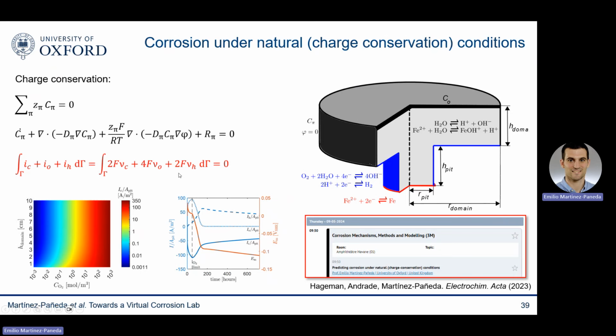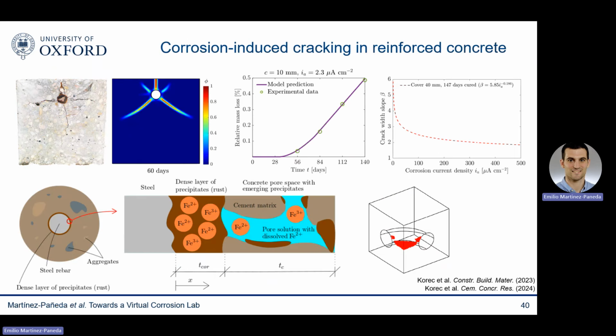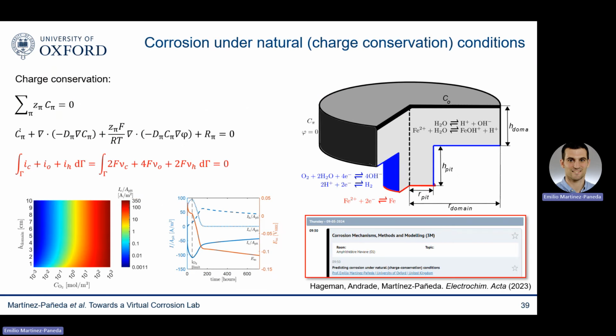We've also combined this type of phase field models with... Oh, let me say one thing first. All the simulations that I showed you so far, as we typically do in our lab, and as you do if you do finite element simulations in commercial codes like COMSOL, assume that you are imposing an applied potential. However, under natural corrosion conditions, you don't have such a condition, right? You don't have any applied potential in your metal. But we can develop models where the metal potential is a degree of freedom, is an output of the model, where we don't impose any constraints, and we can simulate corrosion under natural charge conservation conditions.